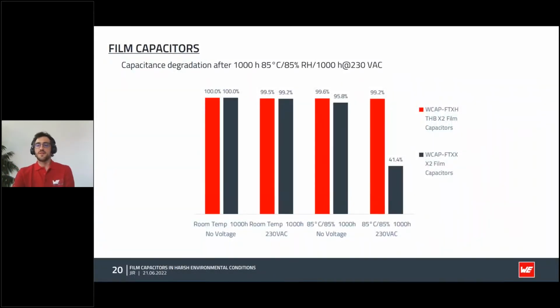So we performed the 85 test with 1000 hours with the mains voltage load of around 230 volts. This was the mains voltage from our headquarters laboratory, so lots of variation happened during the 42 something days, as well as voltage transients. To see the effect of each factor, we connected some components also at room temperature outside of the climate chamber. And also some parts inside of the chamber were not connected to any voltage. As you can see, the combination of harsh conditions and voltage damaged the components. We were happy to find out that the components could handle the harsh environment when they had no voltage. We were also pleased to see that the THB parts did not suffer any significant degradation, even after a harsh test.